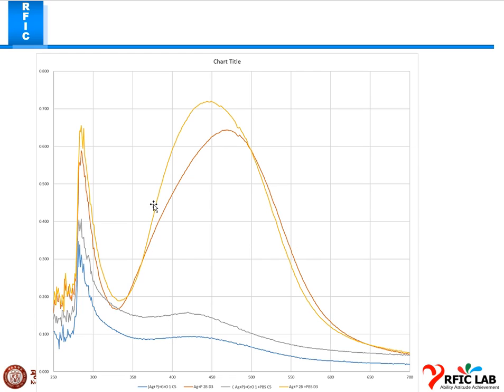And then afterwards we washed the Ag protein complex surface, and then we found the blue shift of the Ag protein complex. So we found that the graphene oxide is not suitable for this research, because in the chemical specification of graphene oxide, the graphene flake size is 0.3 microns. It means 300 nanometer size.